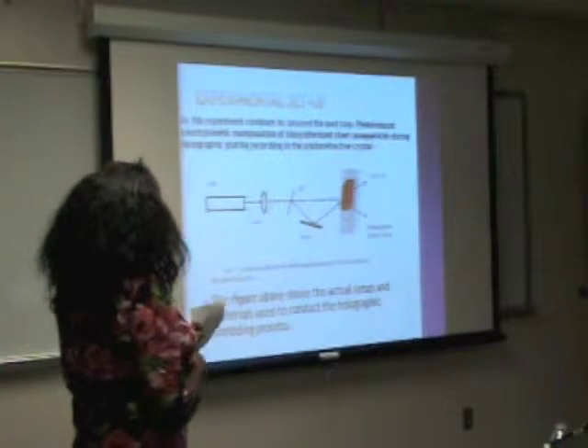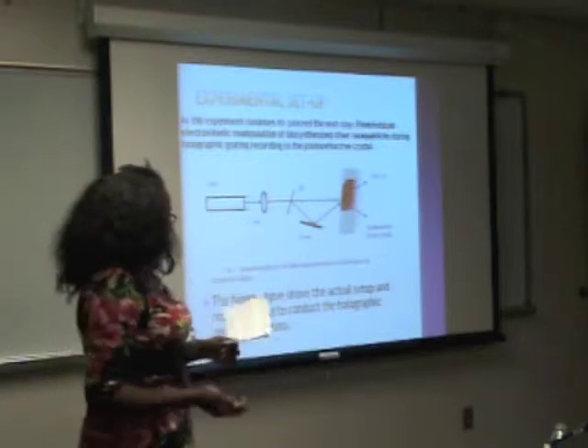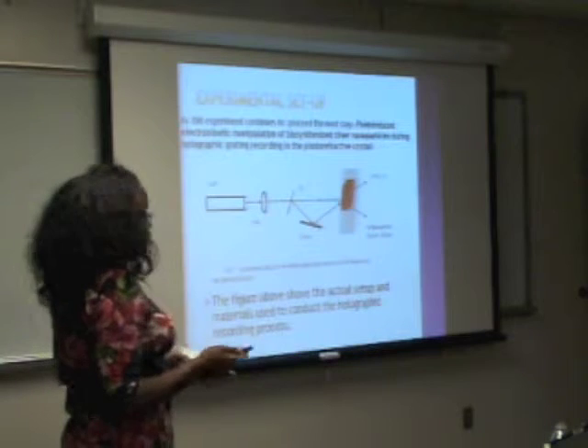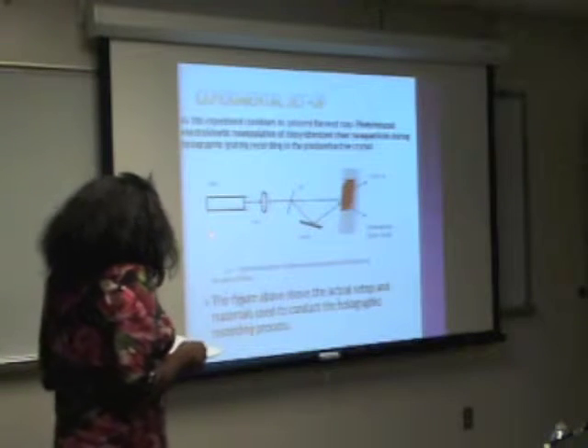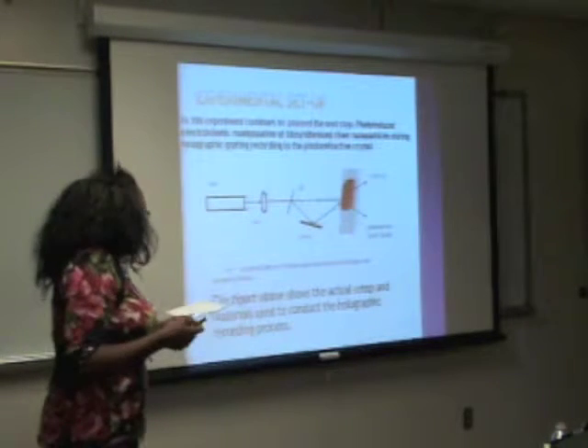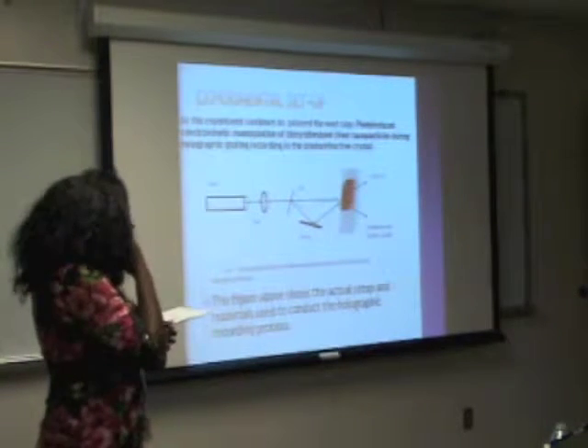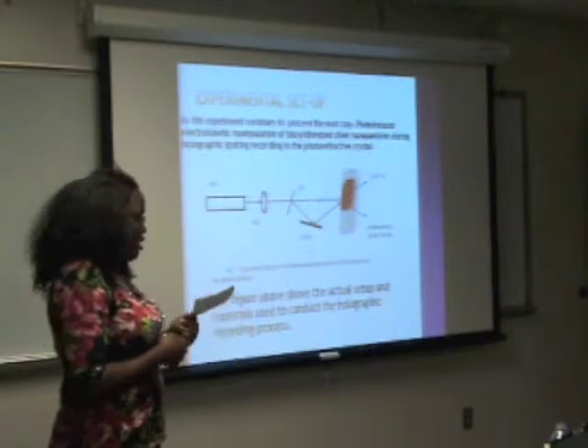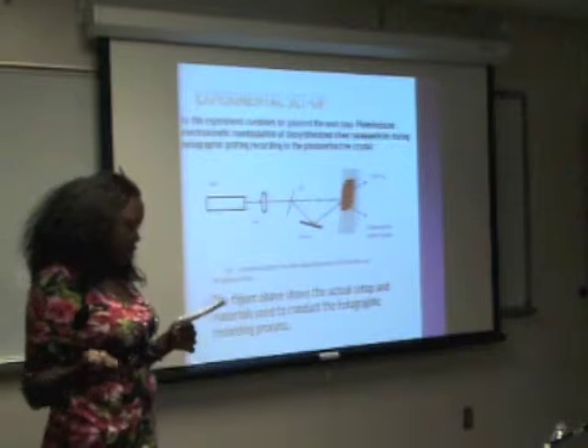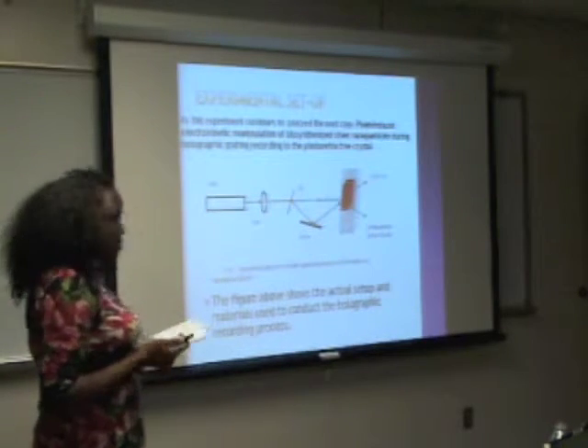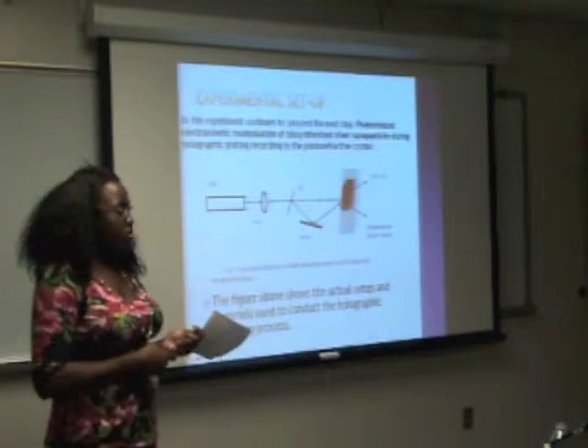This was the experimental setup of the actual holographic grating recording. The figure above shows the actual setup and the materials used. Basically, this is the laser, which beams light through the lens and spans the beam out. A beam splitter was used to split the beam into two, and then this mirror was used to reflect the second beam. When we adjusted the distance, we created a two-beam coupling for holographic recording with an iron-doped lithium niobate crystal.